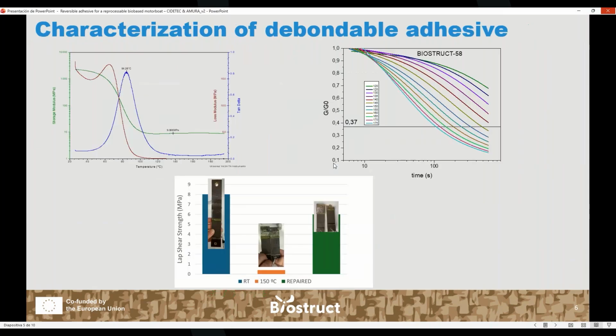Okay, so regarding the properties of this debondable adhesive, we performed the dynamomechanical analysis. We obtain an adhesive having a TG of around 85 degrees, and as you can see, above this glass transition temperature, we still obtain a cross-linked material because it's associative. Here we can see that we obtain a plateau of the storage modulus above this TG.